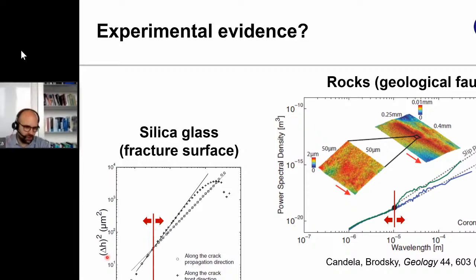So this is again the delta H, so the autocorrelation function is a function of distance. And you see that these scaling properties change at some point, and this length scale probably corresponds to the size of the process zone. The right one is sliding rocks, again from Emily Brodsky's group, that shows something very similar.